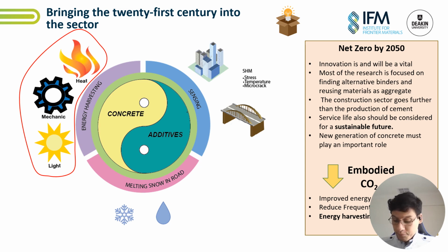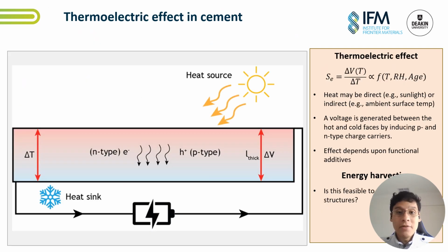But how can I do this? Well, I do this through the thermoelectric effect. The thermoelectric effect produces usable electricity through a temperature gradient between two surfaces. And we measure the thermoelectric effect through the Seebeck coefficient. The Seebeck coefficient can be calculated by measuring the voltage across the temperature gradient between both surfaces. The Seebeck coefficient can be negative or positive. If negative, it means that electrons are the main carriers and it is known as an N-type material. If it is positive, holes are the main carriers and it is known as a P-type material.